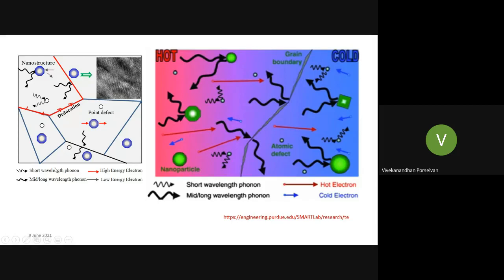And if you look at it, the point defects possibly scatter the short wavelength phonons, whereas the grain boundary or grain boundary junction is more effective in scattering the mid wavelength or long wavelength phonons. In a similar way, we have the charge carrier, right? That is possibly the holes or the electrons. So it depends upon the nature of the doping that you are doing with the bulk material.